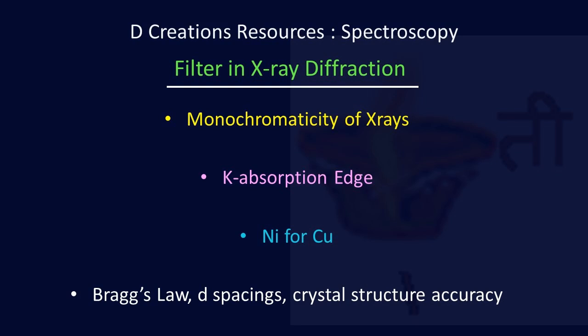So what is going to happen? Wavelengths shorter than the nickel K edge, like copper K beta, are going to be strongly absorbed by the nickel filter, while wavelengths longer than the nickel K edge, like copper K alpha, are going to be transmitted more readily, although some absorption can still occur. So if you carefully select the thickness of the nickel filter, the intensity of the unwanted copper K beta radiation can be significantly reduced, while still allowing a significant portion of the desired copper K alpha radiation to pass through.